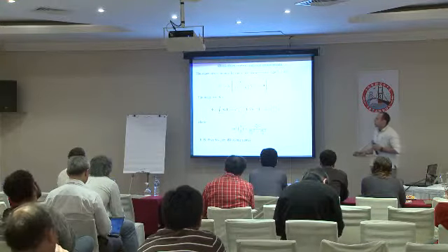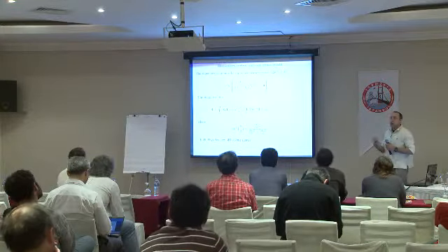And that means if you try to set up a vortex with phase winding in only one component, then this vortex will have logarithmically divergent energy, similar to a vortex in a Gross-Pitaevskii functional. In that case, the magnetic flux carried by an elementary vortex will be only a fraction of the flux quantum, and it will come with logarithmically divergent energy.